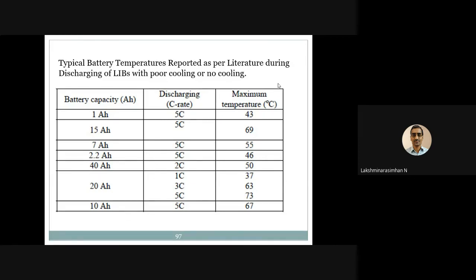So even for a 15 ampere hour battery, they were able to control the temperature to 69 degrees centigrade. That is good, because it's 5C operation. So 5C is a big operation. Even the 10 ampere hour battery with 5C operation, you see 50 amperes will be drawn in 1/5 of an hour. Therefore, it's in 12 minutes.